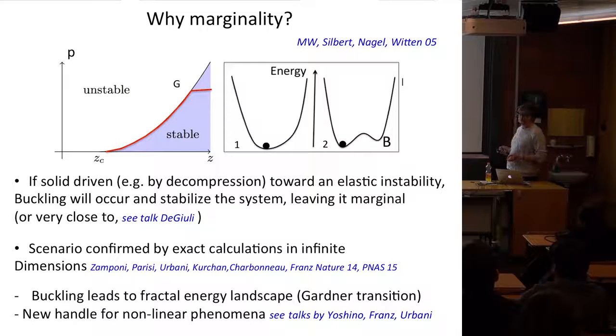What's very exciting about this result is that actually they also tell you something new. They tell you that when you reach this point, and you have this sort of sequence of buckling events, with this method you can actually compute the statistics of the energy landscape. And what they found is that when you hit this line, actually the energy landscape becomes fractal. So this succession of buckling events leads to a fractal energy landscape. And that gives you a new handle to think about nonlinear phenomena or two-step relaxation processes or things like that. And this is something I will not discuss because that will be discussed actually in this conference by various authors.